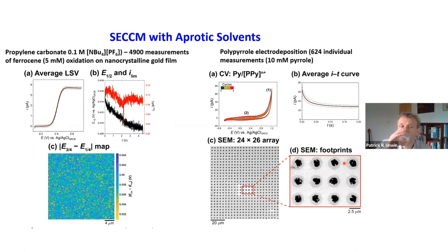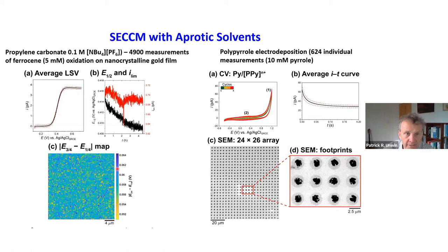I'm going to mainly talk about work in aqueous solution. But Cameron very recently showed that SECCM can be used in a very straightforward manner with aprotic solvents — the types of solvents used in battery electrodes. He did the same kind of measurements: looking at droplet stability when landing on a surface, doing electrodeposition measurements, looking at footprints, and showing that simple outer sphere redox processes are very consistent across the surface.